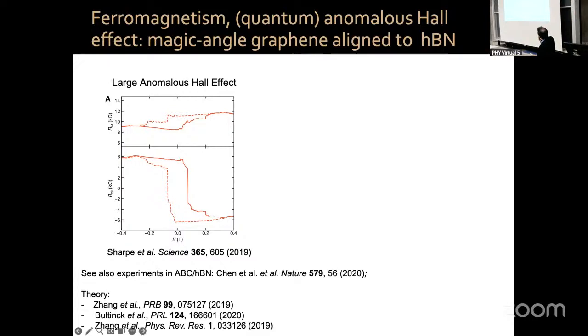In magic angle twisted bilayer graphene aligned to hexagonal boron nitride, you break the symmetry of the system, because now the boron and nitrogen atoms break the symmetry between the carbon atoms, and you can realize this effect.